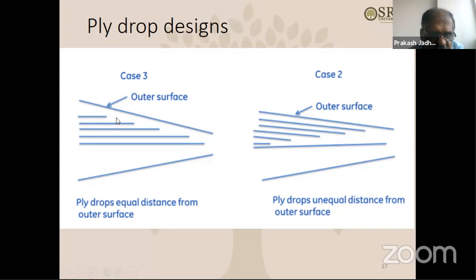When the plies are getting dropped, if they are equidistant from the surface, this is one design case. In the other design case, we were dropping the plies in a different way. As you can see, here the topmost plies are dropped first and then consecutively the others are dropped. Here it is different. Here the middlemost plies are dropped first and then other plies drop like this. So this is another design, and this also we tried. So what is the difference here? Here all the ply drops are near the surface. Here all the ply drops are not near the surface. Like this ply drop is near the surface, this one is near, but other ply drops are getting away from the surface. While in this case, all the ply drops are near the surface. So these are the different things that we tried.